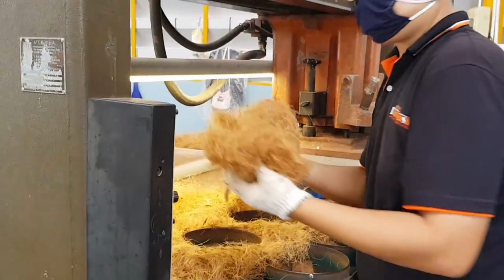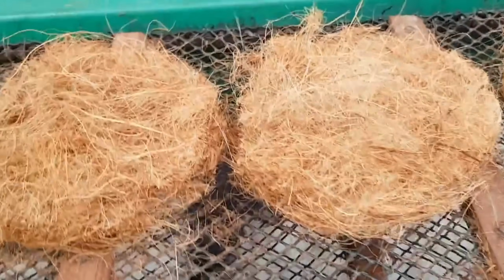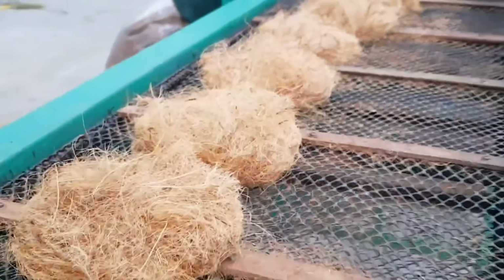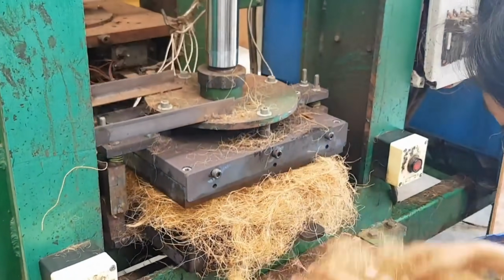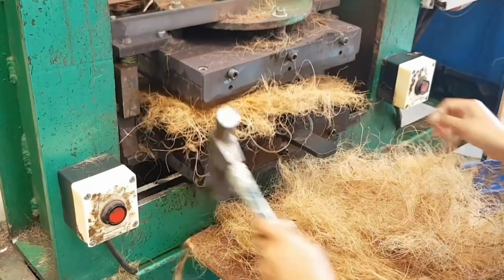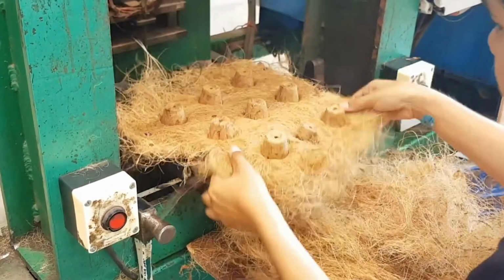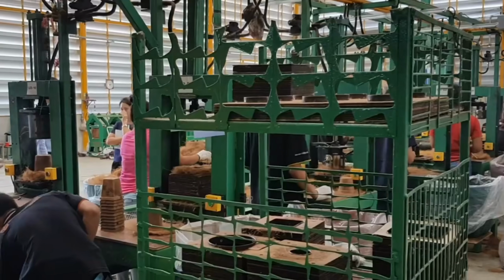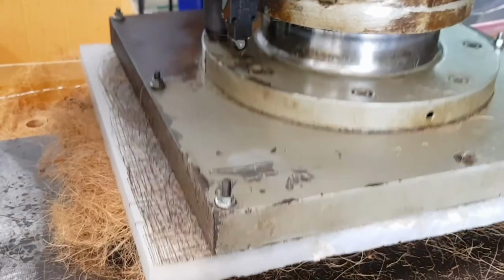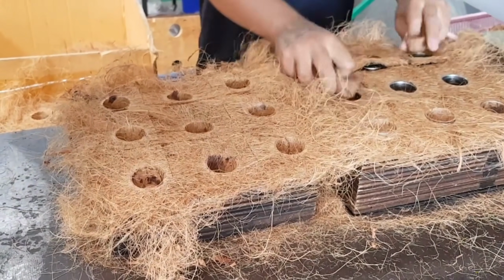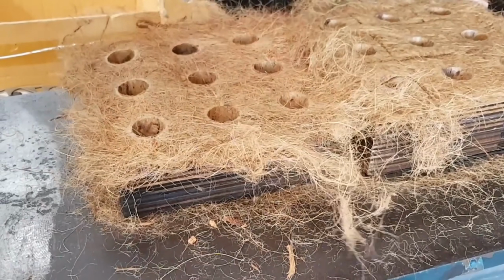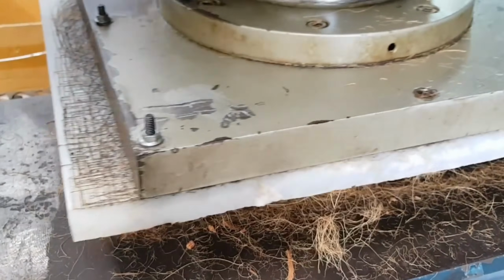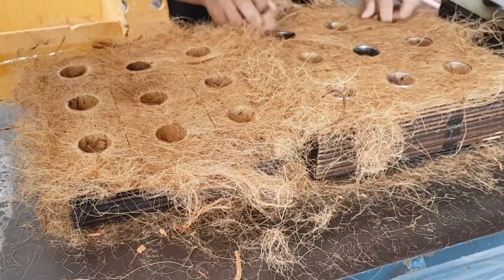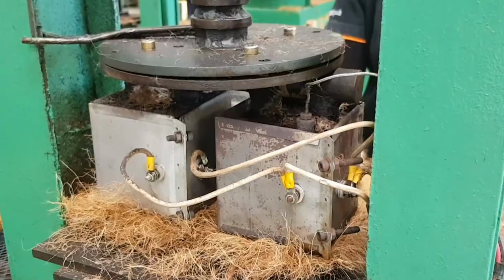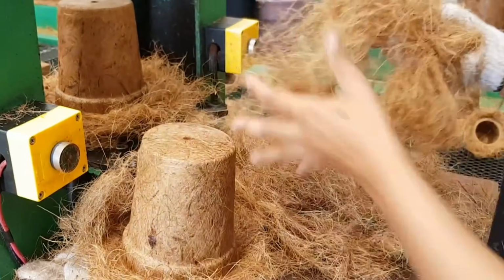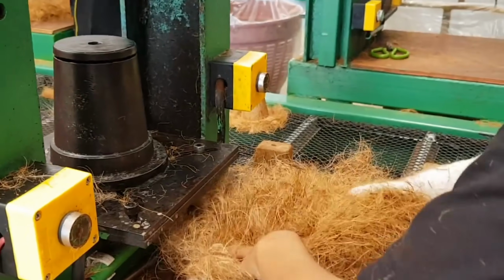When the mold closes, the fibers are subjected to intense pressure, typically between 3 and 8 tons, combined with high heat. Under these conditions, the natural lignin within the coconut husk softens and flows, binding the fibers together from within. This unique mechanism allows the material to take shape without the use of any chemical adhesives, relying solely on the coconut's own organic resin. Only a few seconds later, the mold opens to reveal fully formed biodegradable coir pots. Lightweight, breathable, well-drained, moisture-retentive, and capable of breaking down completely in soil within months.